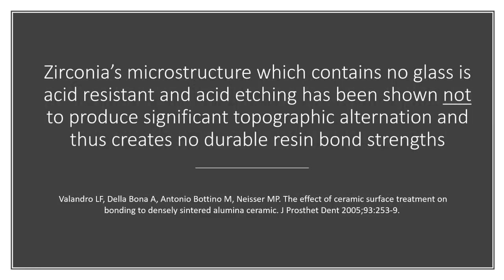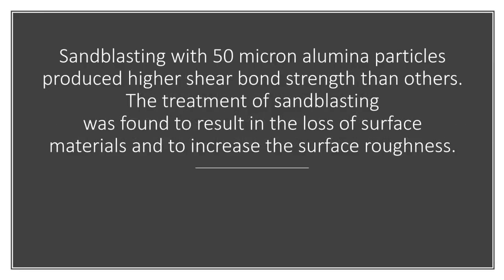So you have to also understand zirconia, as a ceramic, has no glass. It is acid resistant and is resistant to acid etching. And it's been shown not to produce significant topographic alteration internally. So acid etching is not what you want to be doing. So let's talk sandblasting. Sandblasting's okay. Sandblasting with 50 micron alumina particles, do you really know how big or small your particles are? Just asking. They produce higher shear bond strengths. Why? What you're really doing is you're increasing the surface roughness. That's really what you're doing internally.